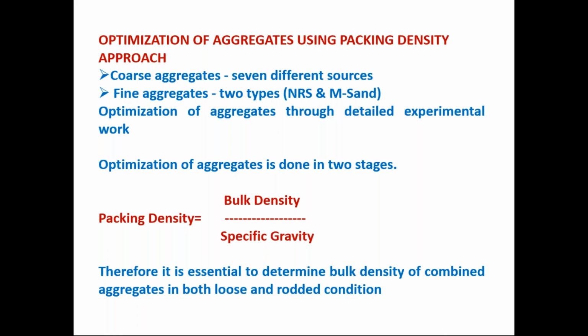Now, once we improve the quality of aggregate by the production method, that is the VSI aggregate method, we can really do the optimization of aggregates using packing density. Because if we can select the aggregates in such a way, we get the highest packing density. What is the advantage of this highest packing density? Higher the packing density, lower will be the voids. Lower voids means the cement paste required will be less. So we can achieve economy in cement. At the same time, we cannot use a harsh mix going on the basis of packing density. You need slightly more paste than required by the packing density method or optimal density method.